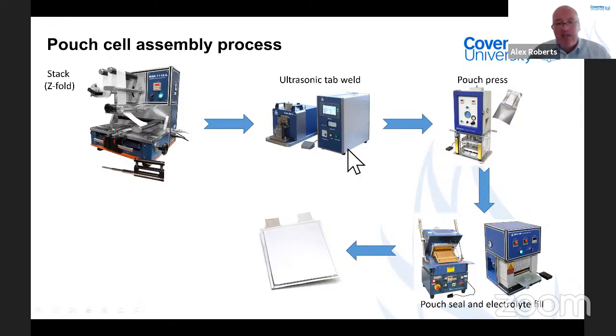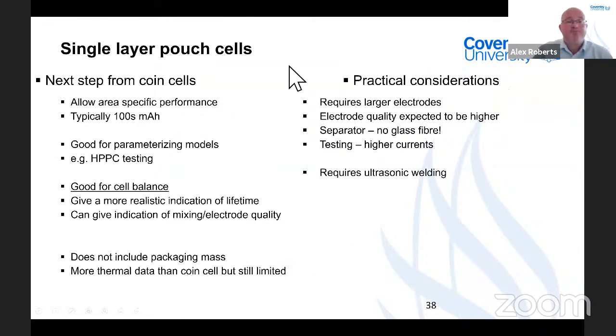And this casing is a laminated aluminium material. And this is very often similar to what you'd find in a coffee bag, but it's much, much higher grade. It's much, much higher specification and thicker to make sure you don't get air or oxygen or moisture coming through. Then you go through a sealing process where you'll seal three edges and then finally fill with electrolyte and move forward to the various formation stages that come on to give you a pouch cell.